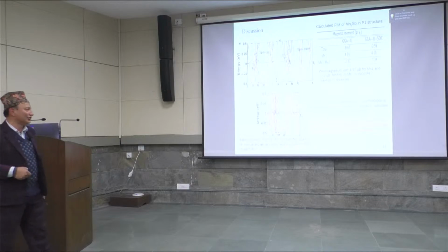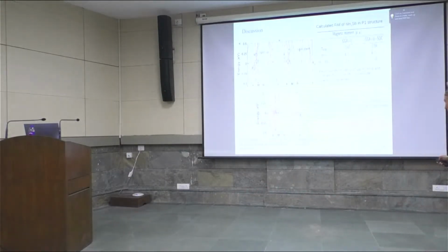While looking at the spin up and spin down, we got some direct gap close to the Fermi level. There is a topological feature at the Fermi level between X and Y along high symmetry directions. When we use SOC, these gaps are more pronounced. We are not moving towards the topological features here, but we think it may be applicable for topological study, and we are moving towards that also. We'll do it later on.